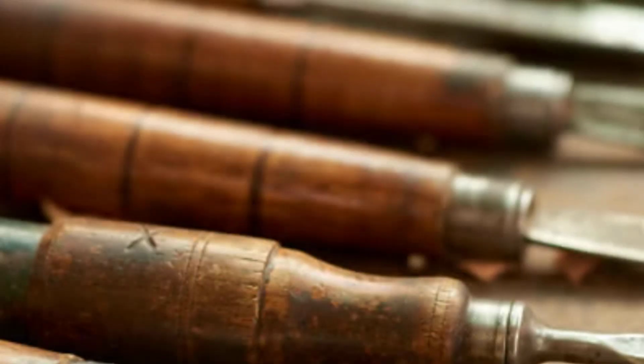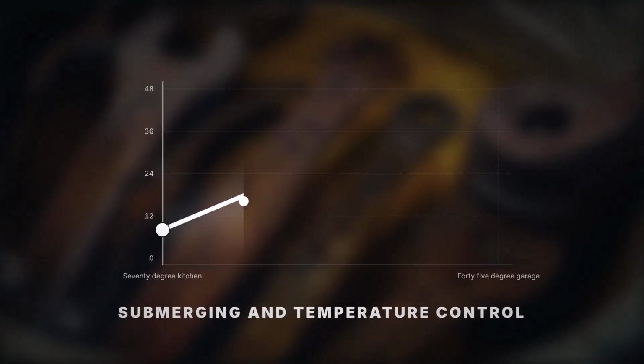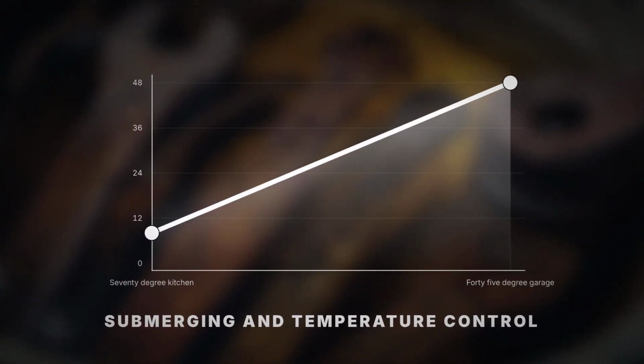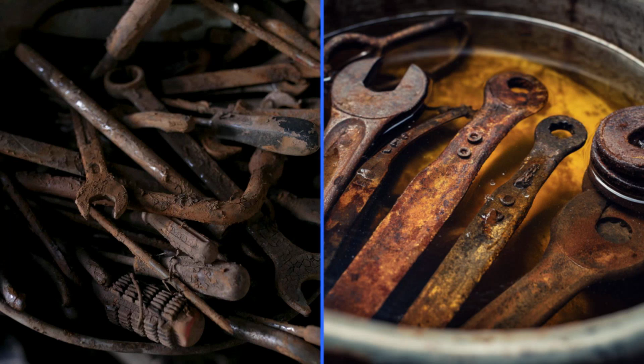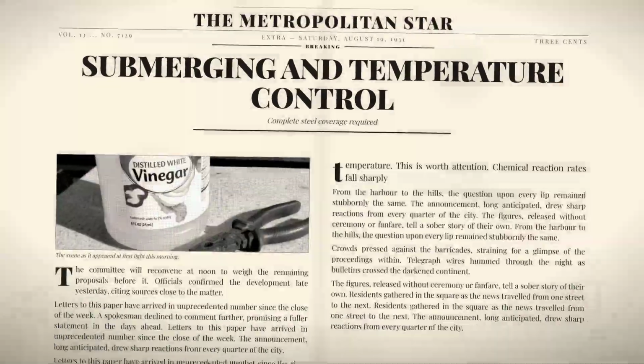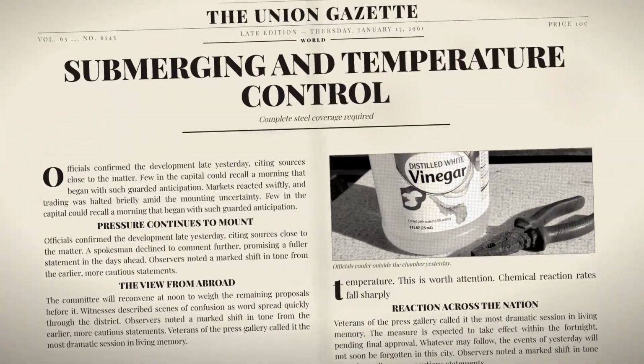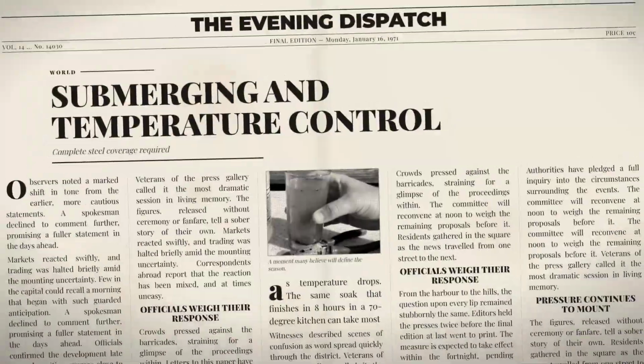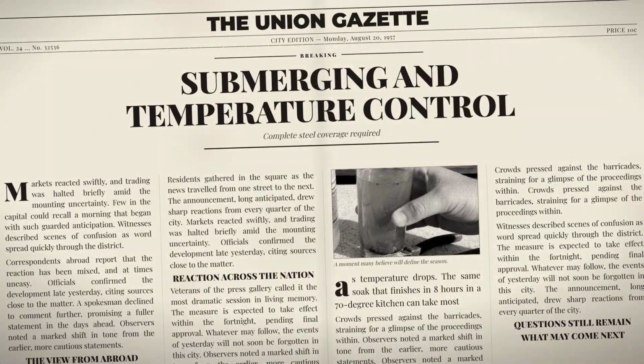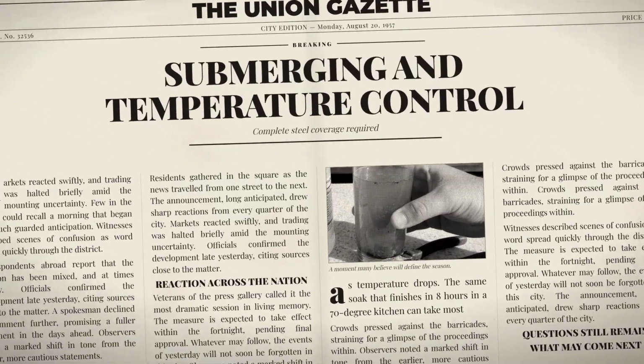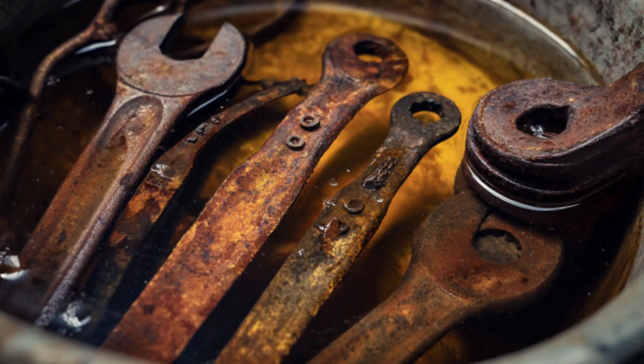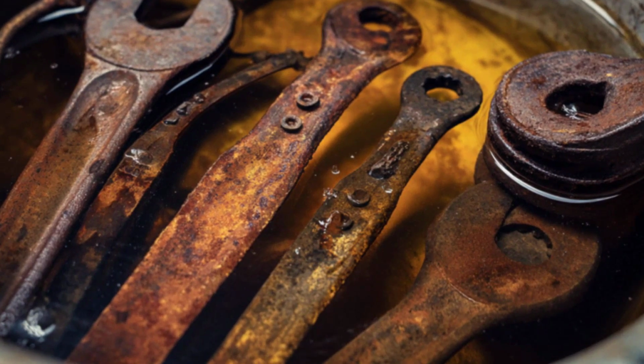Completely matters. If part of the blade sits above the surface, you get a hard line at the waterline where one side has been chemically stripped and the other has not, and that line will still be visible after everything is finished. Set it somewhere at room temperature. This is worth attention. Chemical reaction rates fall sharply as temperature drops. The same soak that finishes in 8 hours in a 70-degree kitchen can take most of 2 days in a 45-degree garage in November. Bring the bucket indoors.